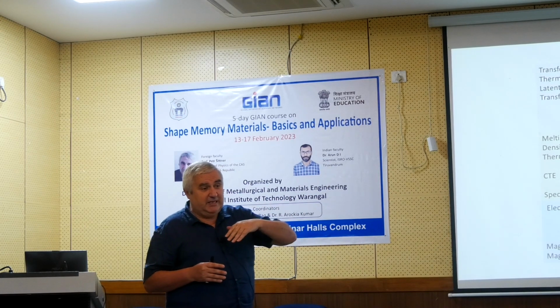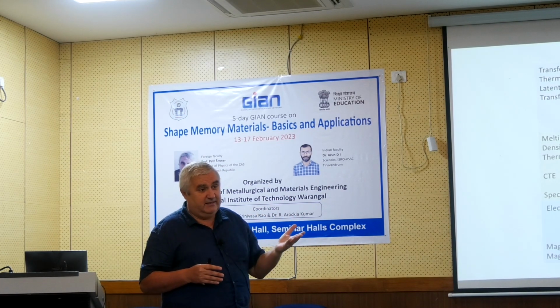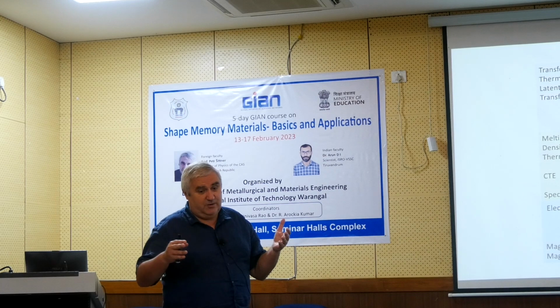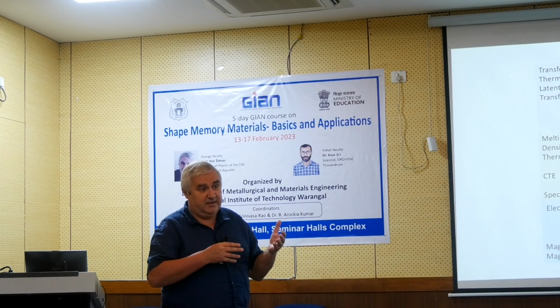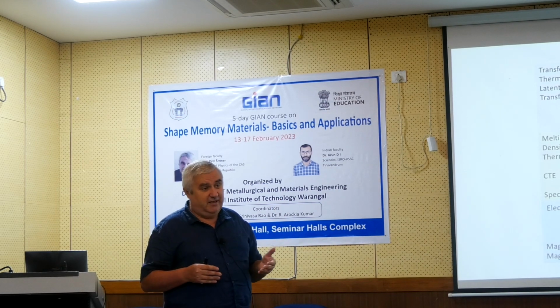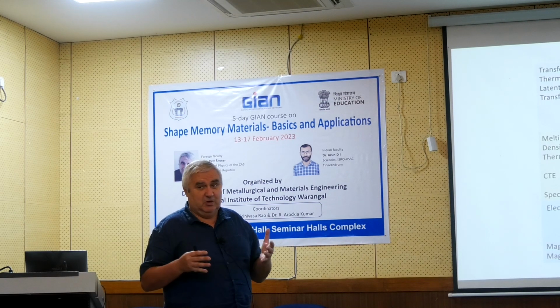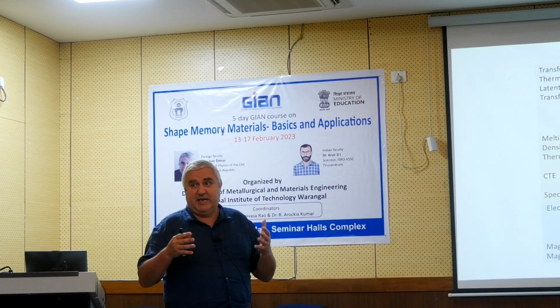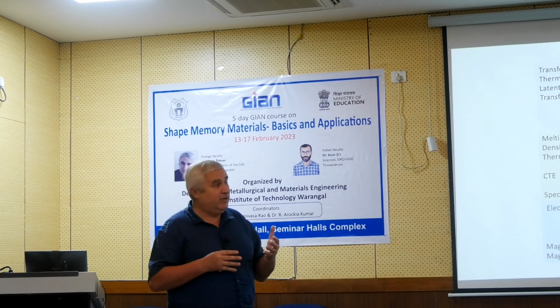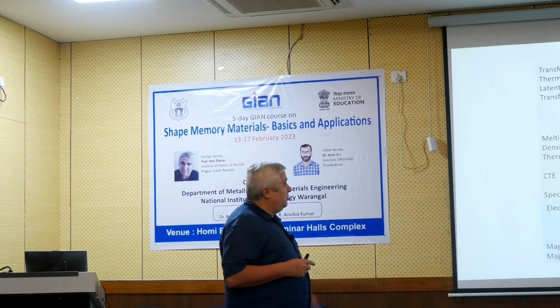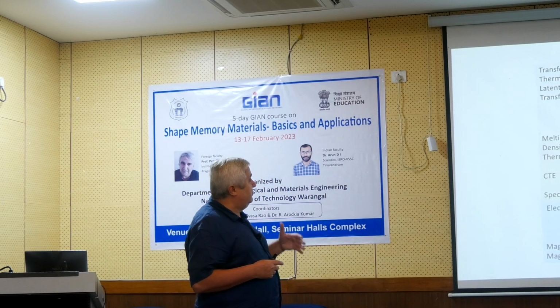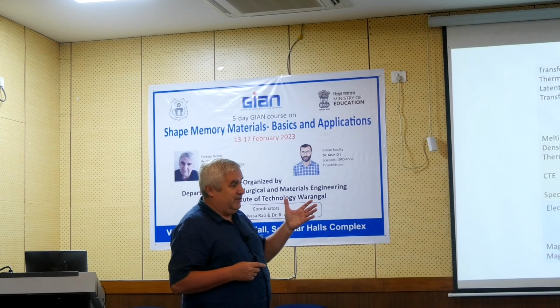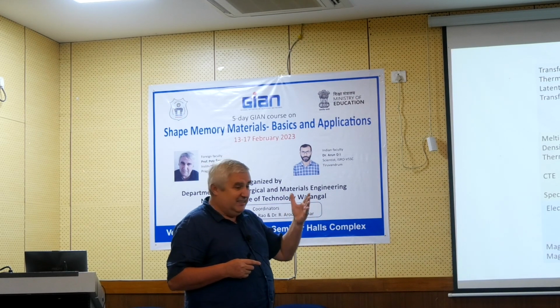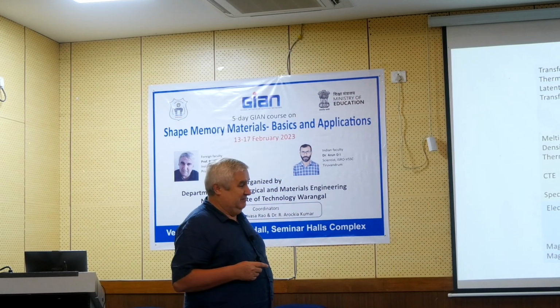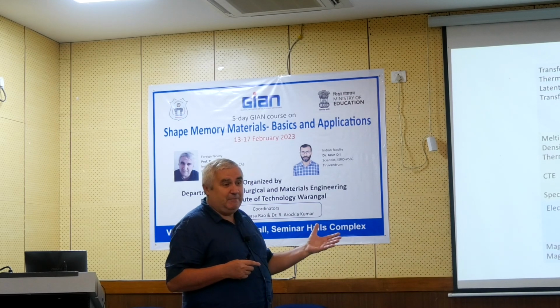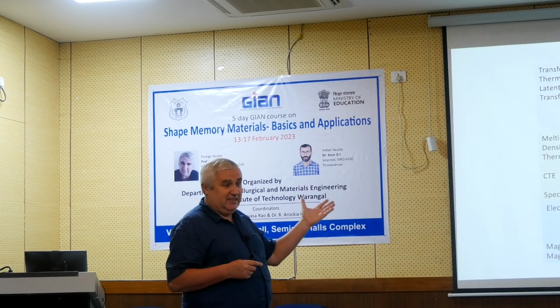But if the material is cycled and trained, and then you do the thermal cycle again, you may have 20, even less, because the material already adapts to this transformation. So don't take it so seriously, but don't expect to have NiTinol with hysteresis of a few degrees or a few megapascal. There will always be significant hysteresis.